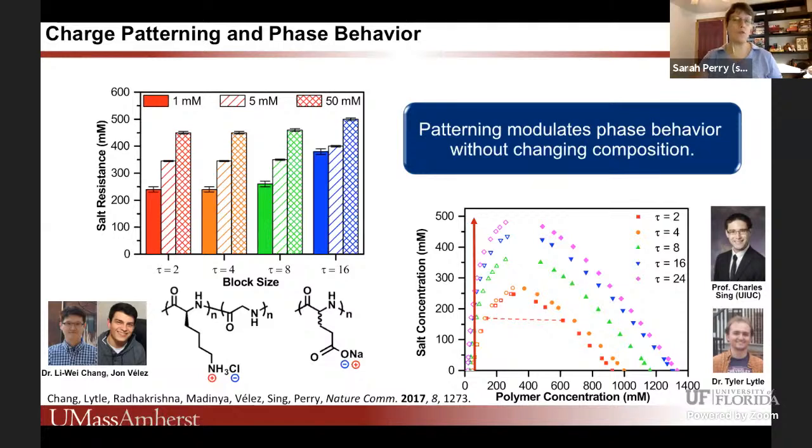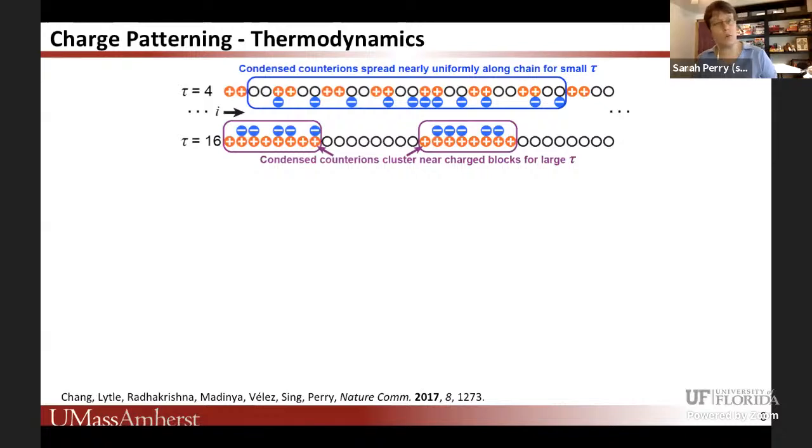And so that's a very simple and powerful statement, but what's really much more interesting is the why that underlies it. And so this is where the simulation work that Charles's lab did really came in to help explain things. So this is just a schematic representation. And you would think that, okay, well, these are materials that form a complex. So probably those interacting materials, the final product, is going to be what dictates the phase behavior, right? And it turns out that's not actually the case. The important consideration is how those polymers are in solution before they ever see an oppositely charged species.